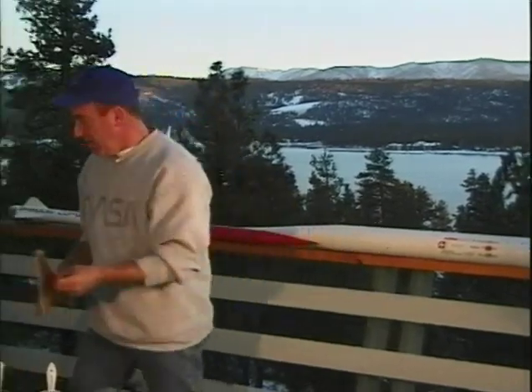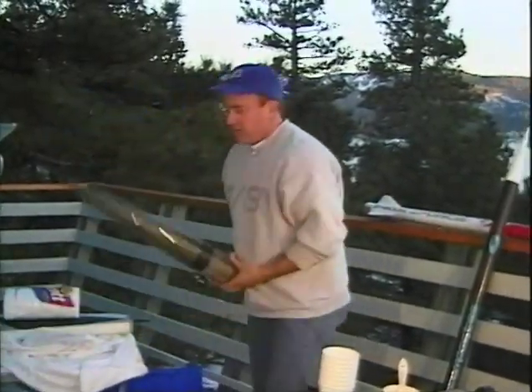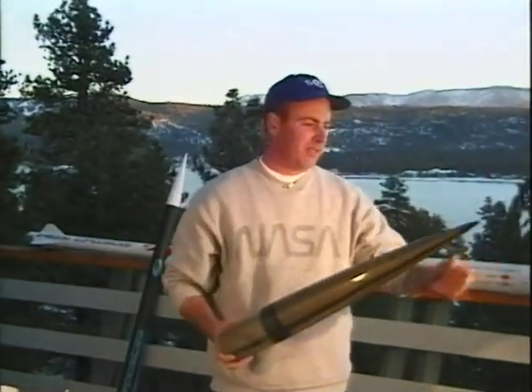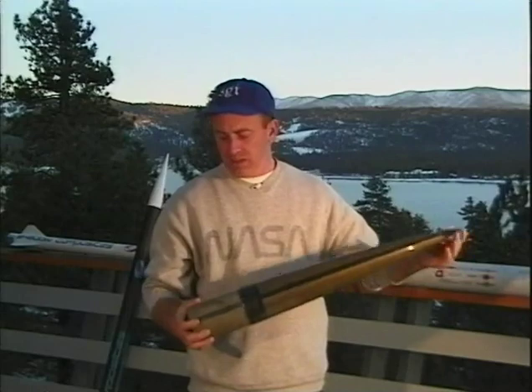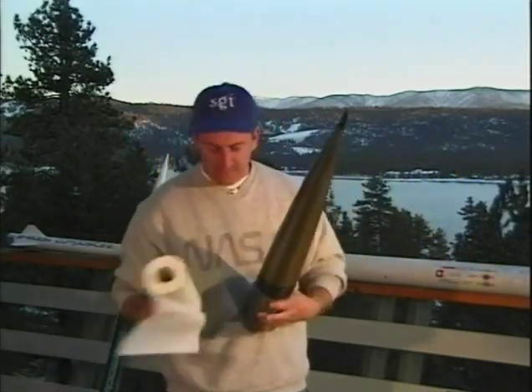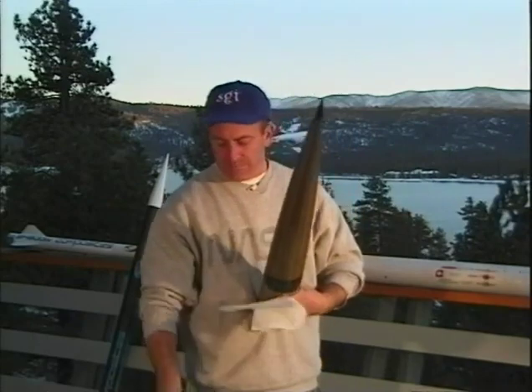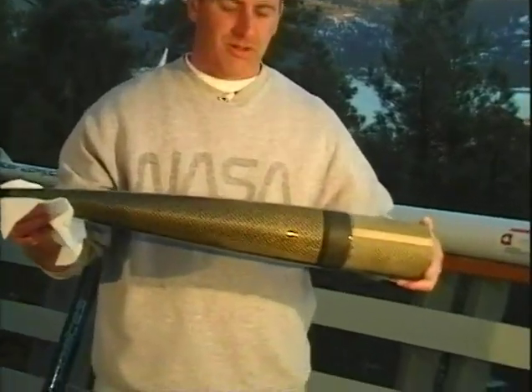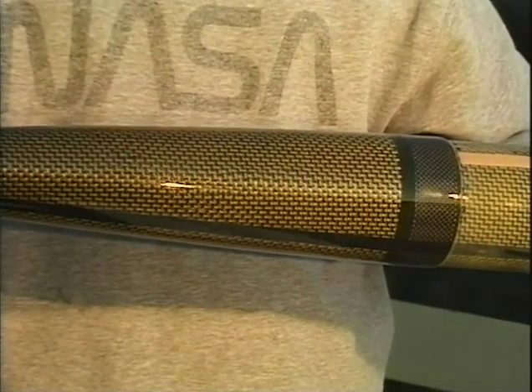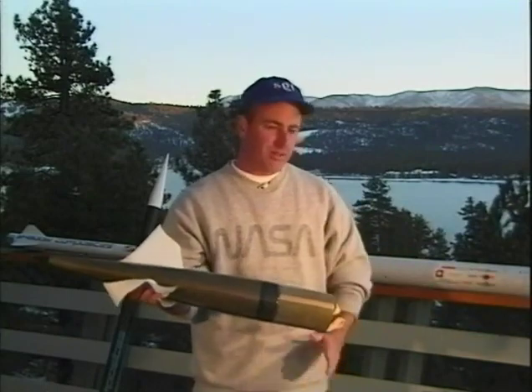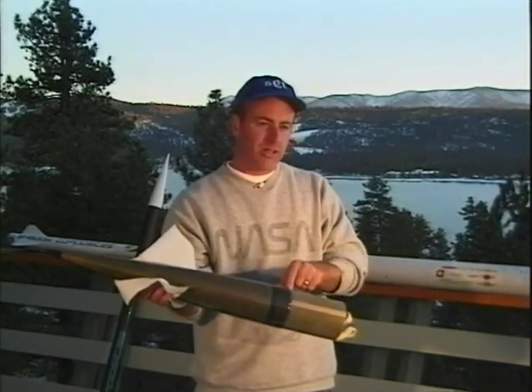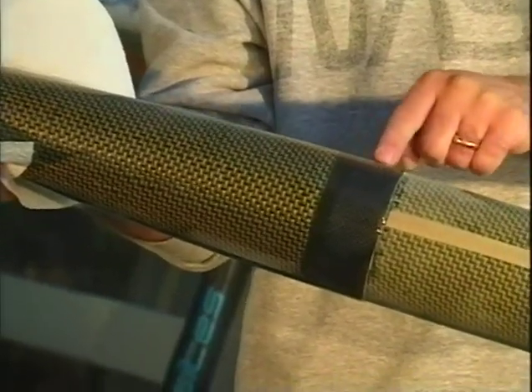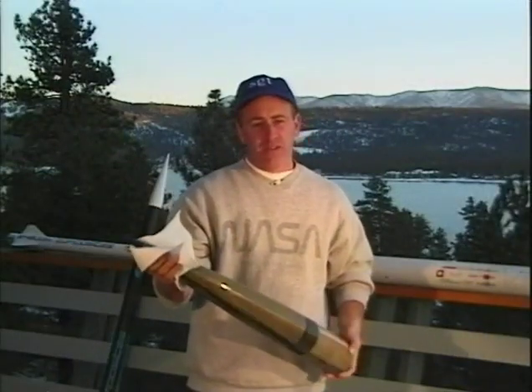So, using this technique, you can do some beautiful things. This is the nose cone from the Trinity rocket. That's the Advanced Composite Technology demonstrator rocket that we made. It's still got dust on it from the last launch. But as you can see, that's a beautiful cone. And it's made using a hybrid cloth of carbon and Kevlar and an epoxy matrix. The technique that I used, that I showed you there, of using the bands of material to create the shoulder on it, on this cone it's created using bands of carbon fiber. So you can do some beautiful stuff with vacuum bagging.